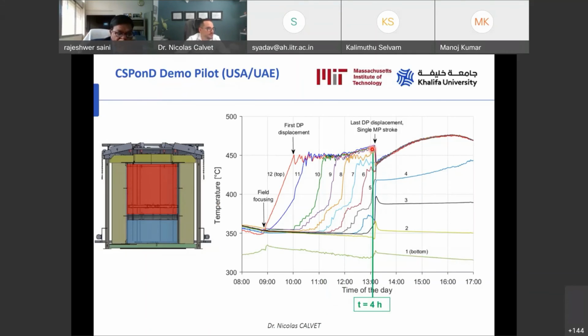You see that we have difficulty reaching the bottom of the tank because the volume of salt is not perfectly transparent like water. So that's why we decided to include a mixing plate. And so you see, we move the mixing plate, and this has an effect to homogenize perfectly the full volume of molten salt. And after that, we see that we are able to reach almost 500 C in this case. So we tested this up to 500 degrees, not yet to 550 due to time constraints, but this is in our plan for the future.